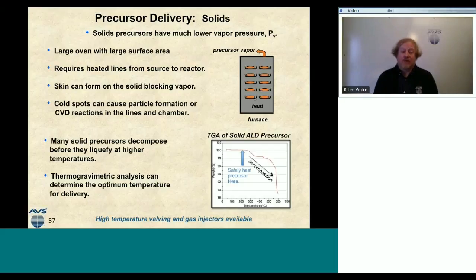Now, many solid precursors, like those wonderful organometallic precursors, will actually decompose before you heat them up to liquefied temperatures. So I can't really just take that precursor and heat it to the liquid phase and then draw the vapor off, because the chemical precursor is going to decompose. So we usually use thermogravimetric analysis to determine the optimum temperature for delivery.